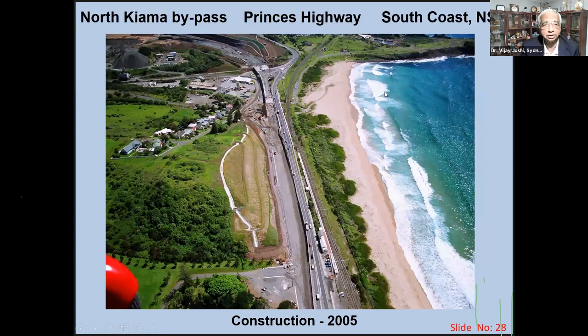Another example of this is North Kiama bypass, which is about 100 to 150 kilometers south of Sydney. I wanted to show you the specific, I mean, those who are in the authority, if you are listening from PWD or any NHAI, you see that this is a quarry available next to the road. But local authority has decided to use the recycled material, and the recycled material was brought about 40 kilometers from the source rather than using the natural material. So how good people are thinking in terms of the environmental cap, and not only the environmental cap, but in terms of the engineering side of it, the road is performing very well. This is almost 15 years. The slag was used in both the layers, and of course in the asphalt top layer too.